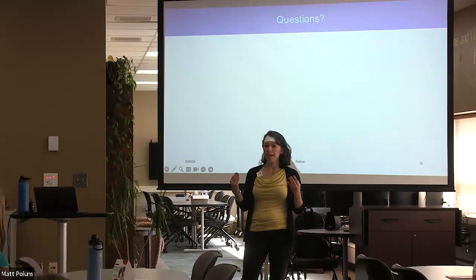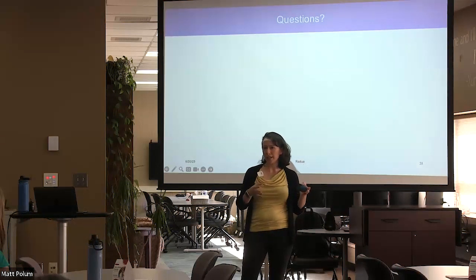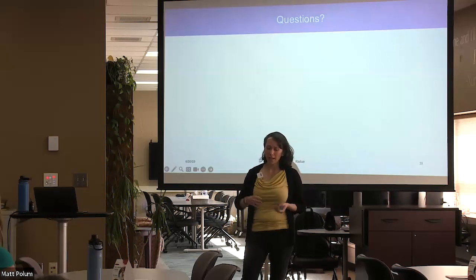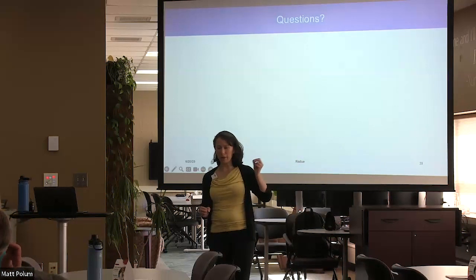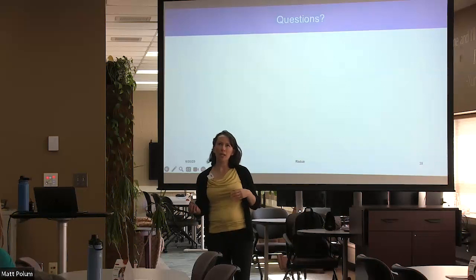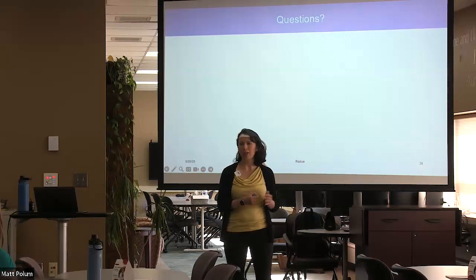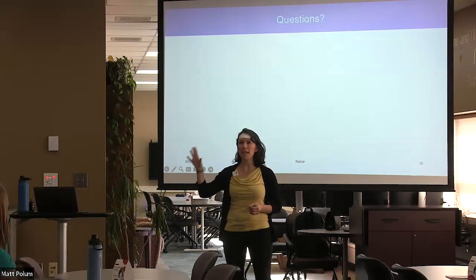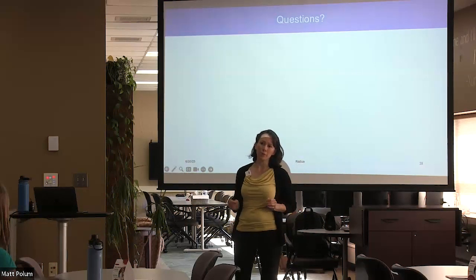So maybe there's both structural change and it's causing more electrons to go to a higher energy state, possibly, or a lower energy state. And yes, Raman and FTIR seem like they're measuring the same thing, but there are vibrational modes that are sensitive to infrared absorption, and there are ones that are just sensitive to Raman spectroscopy. So we can take a peek at different vibrational modes with the two different methods. So that's why I want to incorporate both.